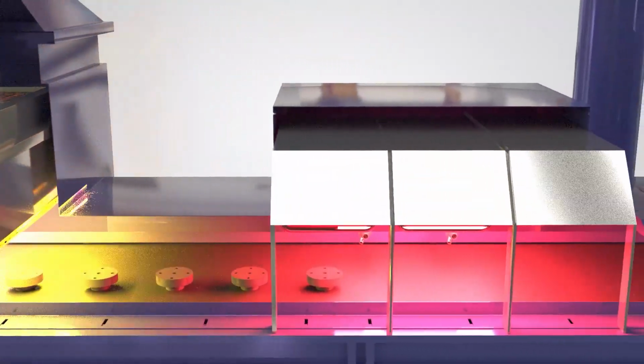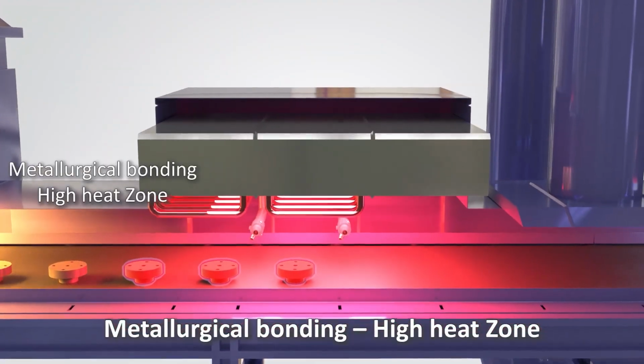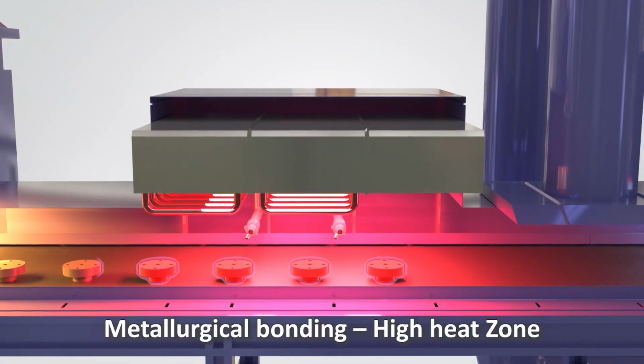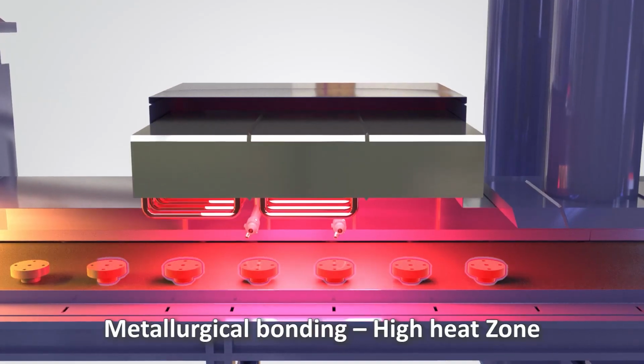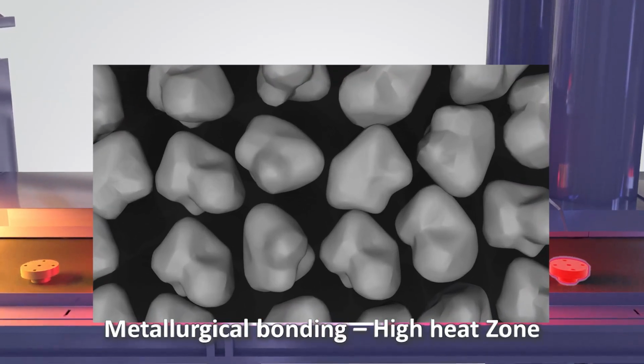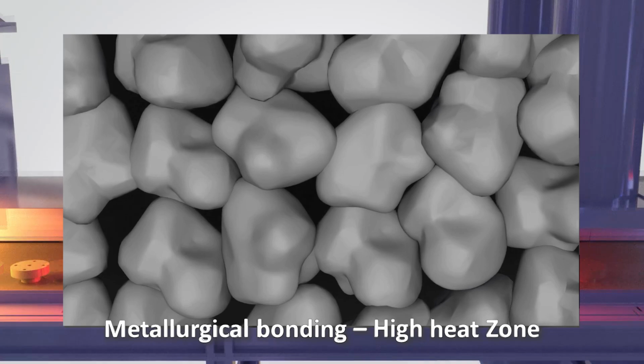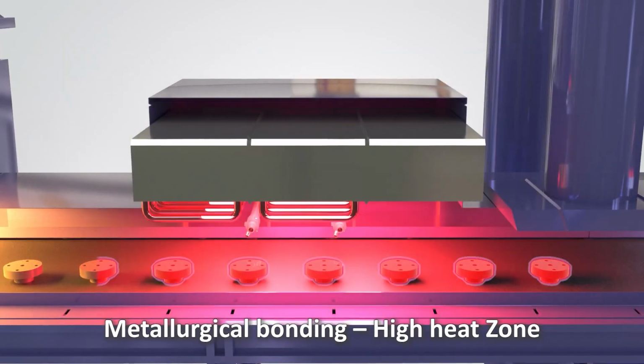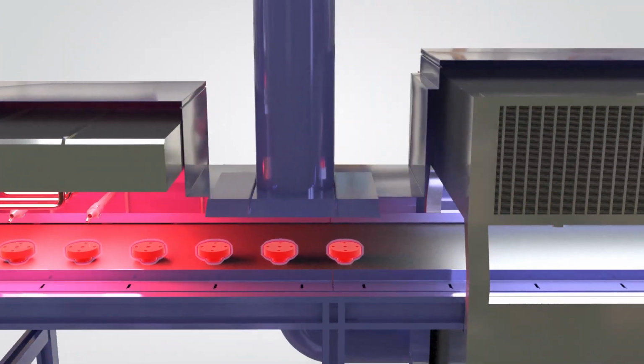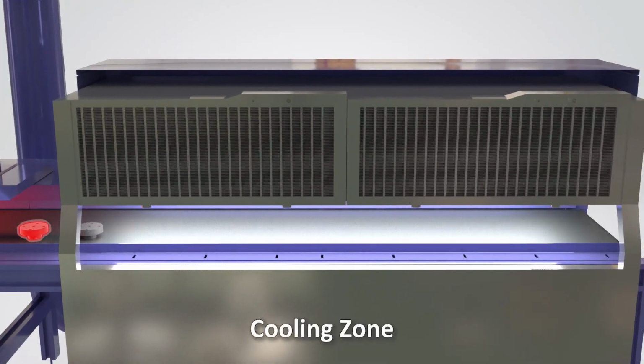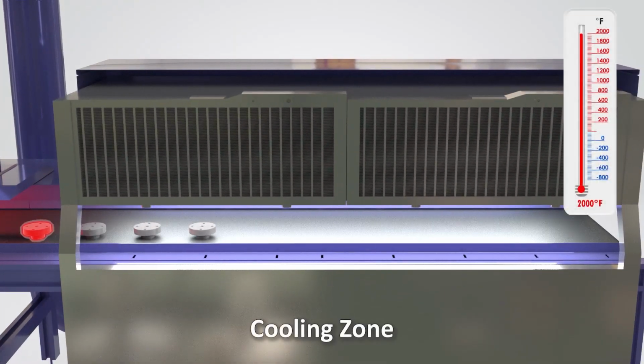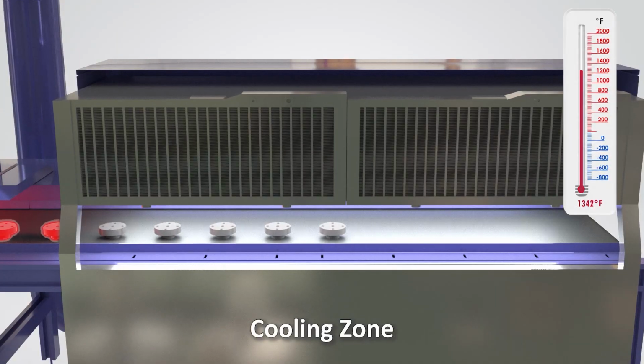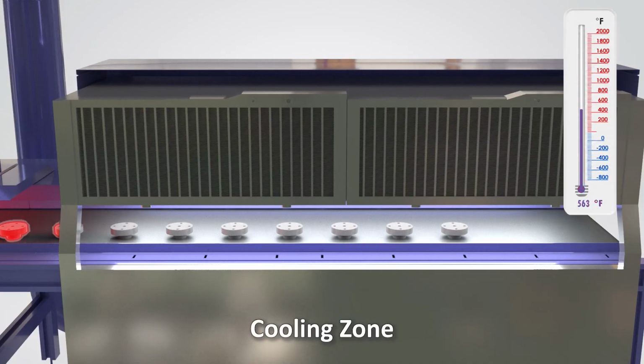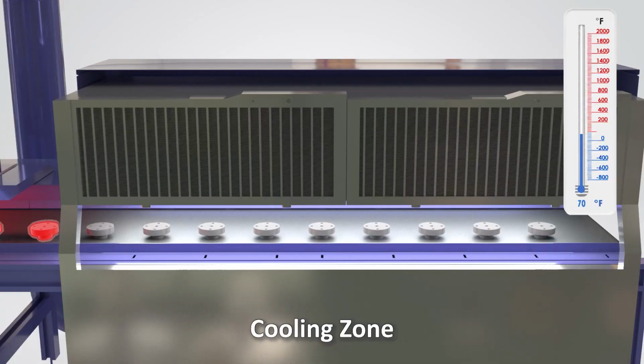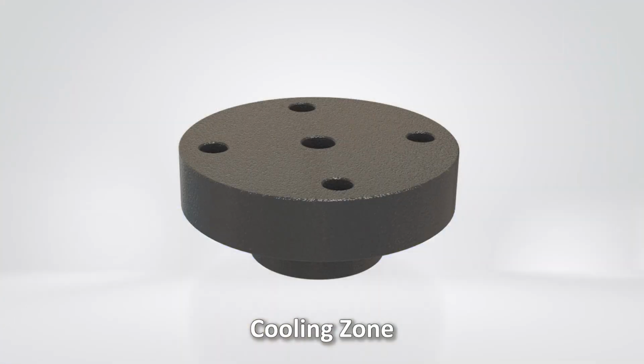As the compacts enter the high heat zone, they are heated to temperatures just below the metal's melting point, creating metallurgical bonding. This results in strong metallurgical bonds, locking them into their final shape. The parts cool in a controlled environment in the final zone of the furnace. The compacts solidify into a final density, locking in the precise dimensions achieved during sintering.